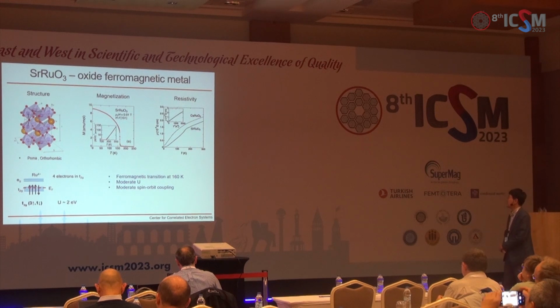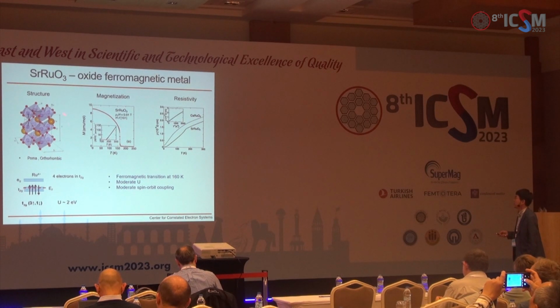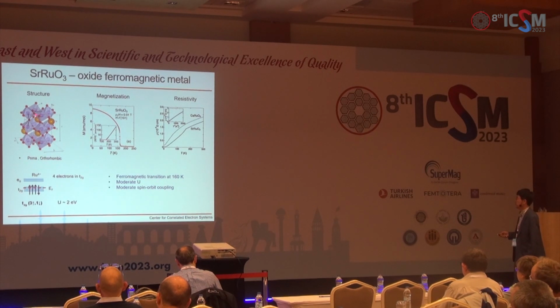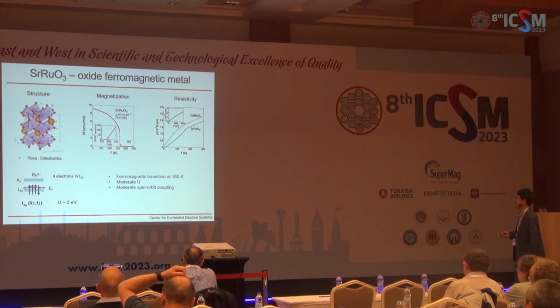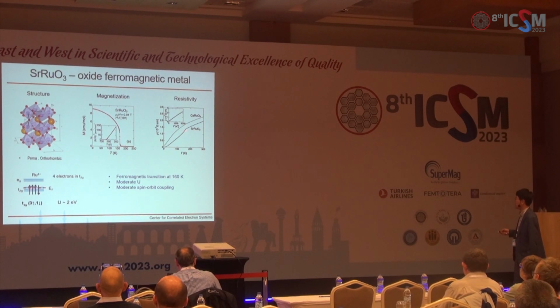So strontium ruthenate is an oxide ferromagnetic metal. It has a pseudo-cubic structure. It's a perovskite with octahedral distortions, and it's in an orthorhombic structure. It's a ferromagnet with a TC around 160 Kelvin. So if you measure magnetization as a function of temperature, it goes up at TC here. The resistivity mostly behaves like a Fermi liquid, but at TC there's a kink because the spin fluctuation is suppressed below TC, so that suddenly becomes a Fermi-liquid-like behavior. Meanwhile here, the resistivity is more or less linear.